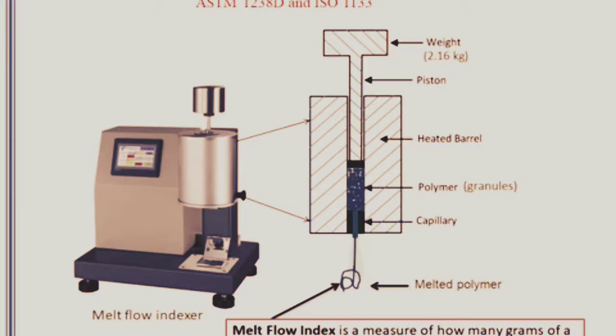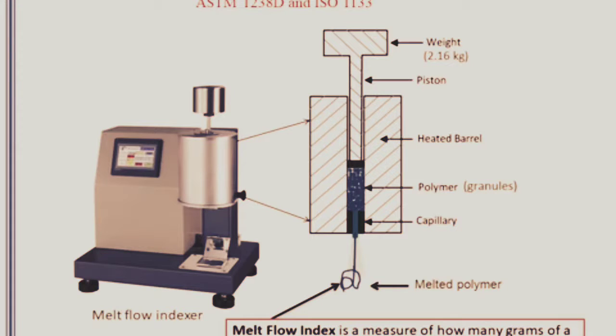MFI testing is carried out according to ASTM D1238 and ISO 1133. Both methods use a standard testing apparatus with a standard capillary of 2 mm diameter. The sample can be in the form of neat polymer pellets or granules, or it can be ground material from a finished thermoplastic product.